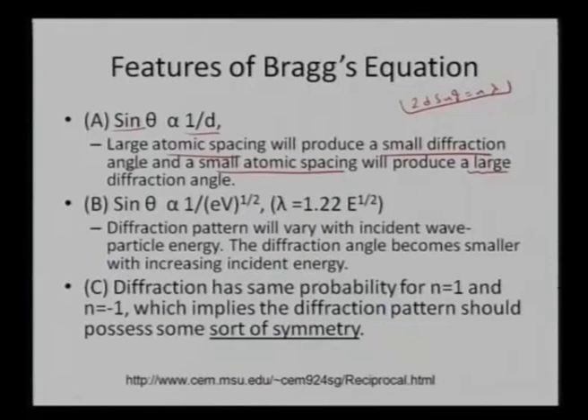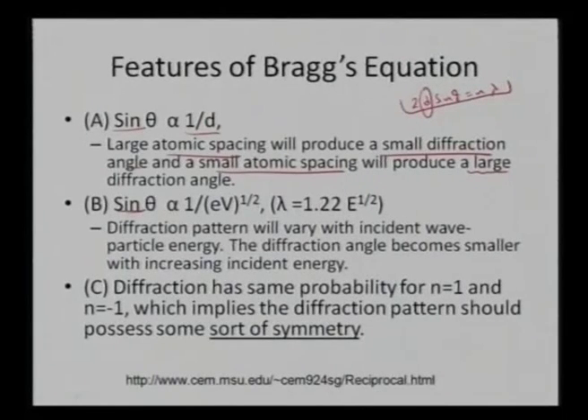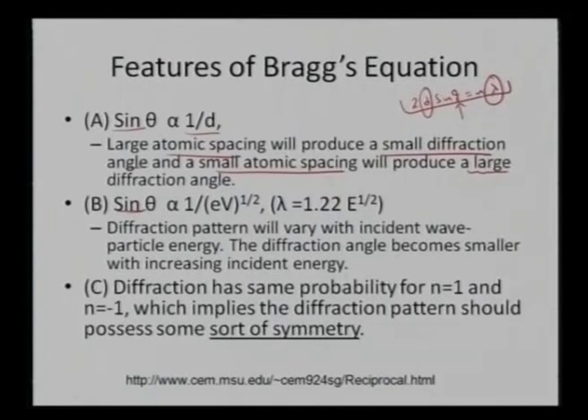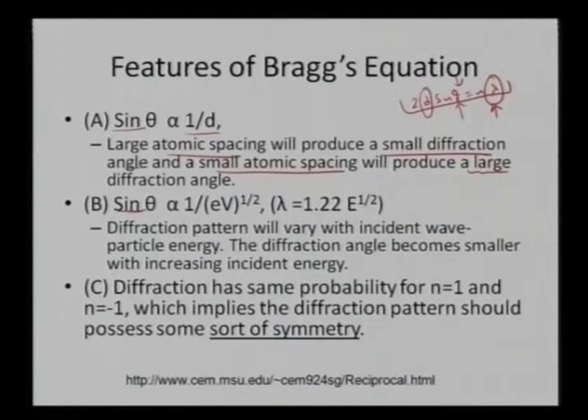Secondly, for a particular interplanar spacing, sin θ is also inversely proportional to energy. If I start increasing λ (decreasing energy), my θ will also decrease. As energy is higher, λ is lower, so θ also has to decrease.